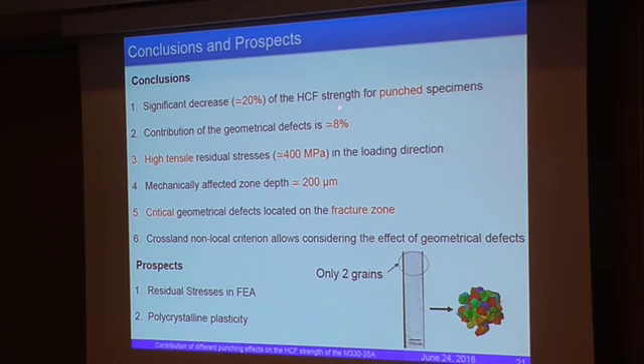The fatigue strength decreases about 20% due to the punching process. The contribution of the geometrical defect is about 8%. The main contribution is also due to the very high tensile residual stresses, which are the same order as the yield stress. And we have a very small affected zone, and we are able to localize the critical geometrical defects in order to apply non-local criteria, Crossland criteria.